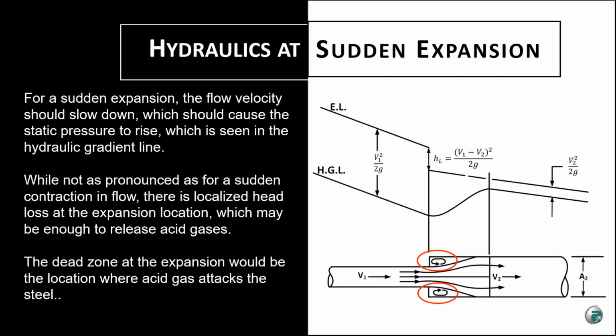Acid gas breakout effects are not as severe in sudden expansions, as you can see from the drawing below, where we go from a smaller diameter pipe to a larger diameter pipe. Inside the larger diameter pipe, the flow velocity will naturally slow down, which means that the difference between the hydraulic gradient line and the energy line reduces, and mostly we'll get potential acid gas breakout from that head loss at the entrance. And if there is acid gas breakout, that acid gas tends to find the dead zone, which is the location immediately downstream of the expansion, and there's a potential for corrosion at that location.